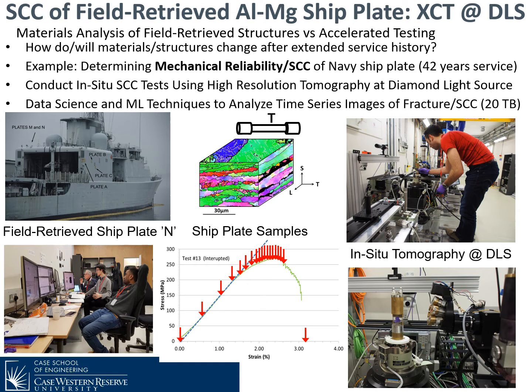The tension sample is in there either in a completely dry or humid or even solution environment, where we can image at a variety of different resolutions depending on the objectives that are used on the right there to capture the evolution of fracture, starting at the very start with zero load and then generating stress strain curves like you can see in the bottom middle, where we take tomograms wherever you see the arrows.